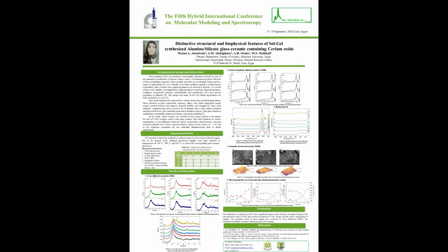Glass density is related to molecular weights. In our investigation, CeO2 rose at the sacrifice of Na2O and CaO, resulting in higher density. The major causes for increased packing density in the glass network are reductions in Vm and Vf. Increased density is related to the high compactness of the glass ceramic formed from the addition of CeO2, which improves the durability and hardness of the samples.